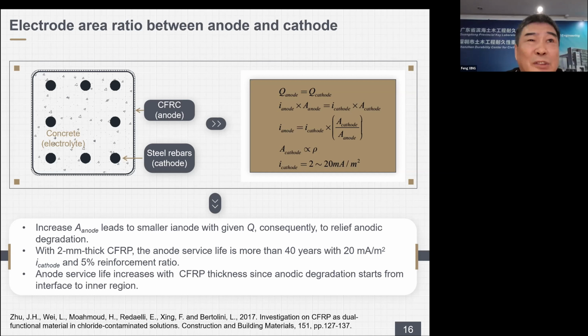Another key problem is the bond matrix. Typically, there are two kinds of bond matrix. Organic matrix, such as epoxy resin, and inorganic matrix, such as cementitious material. The bond matrix in ICCP-SS is not only to transfer strength, but also provide phase boundary of electrochemical reaction. It must be conductive and durable. Epoxy resin is not conductive. Some proven research try to use resin-containing conductive powders to achieve ICCP-SS dual functions.